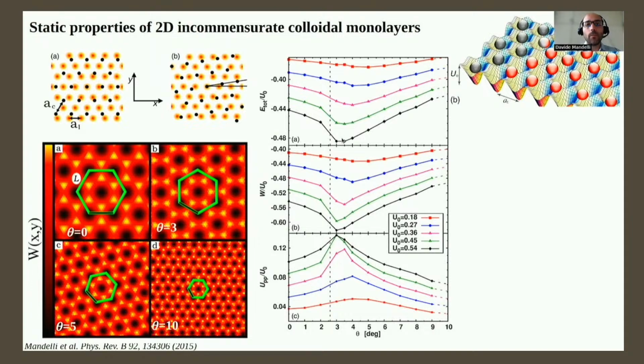To understand what is going on, we can look at the two components of the total energy. We can start by looking at the interparticle Coulomb repulsion energy within the crystal, which is shown in this panel here, which measures in some way the distortions present in the crystal. And we see that as we approach the optimal angle, the distortion, so the interparticle energy, increases. But this increase in interparticle energy is more than counterbalanced by a corresponding decrease in the interaction energy with the substrate potential, meaning that as we approach the optimal angle, the colloidal layer improves its interdigitation with the substrate.